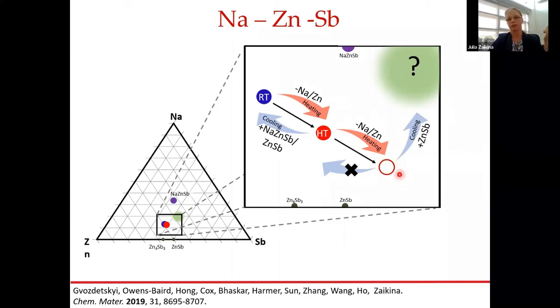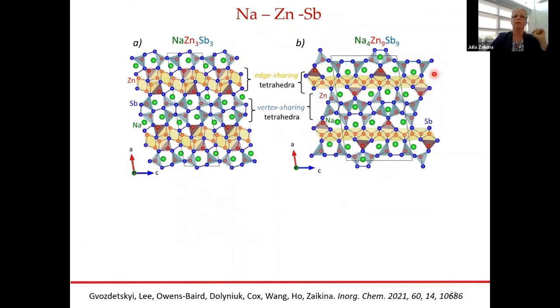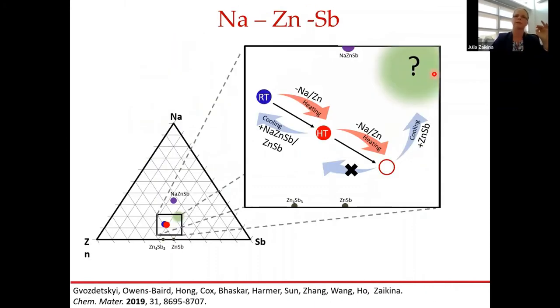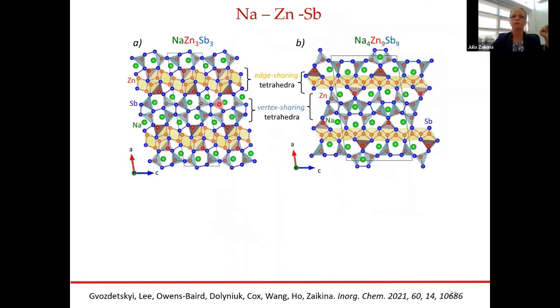And so that composition upon cooling gave us a couple of binaries, but also an indication of a new ternary phase, or maybe even 2 of them or 3 of them. Well, then we did the screening with the hydride synthesis by targeting specific compositions from this region. And what we have found out is that indeed there are 2 new ternary phases. One has 1,3,3 composition, another has composition close to 1,2,2.